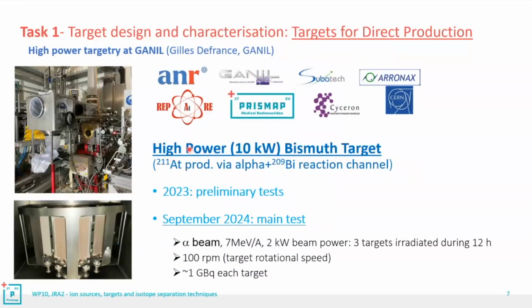At this point, I would like to move to the description of the activities done by Gilles in the context of high-power targetry. In particular, they developed a high-power rotating bismuth target for the production of astatine 211, irradiating the target with high-energy alpha beams. They designed the target and manufactured it during the first period of PRISMAP. Then in 2023, they made the first preliminary test, and in September 2024, they made the most important test, the main test, I would say.